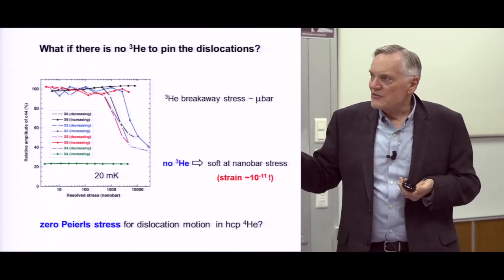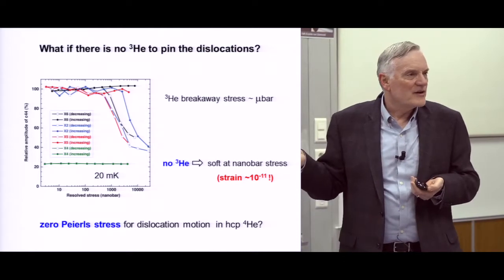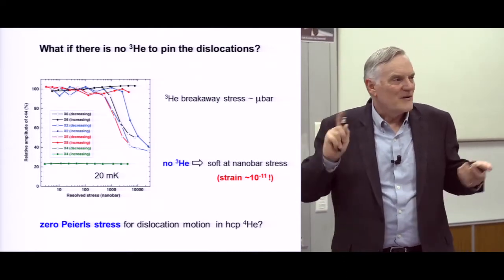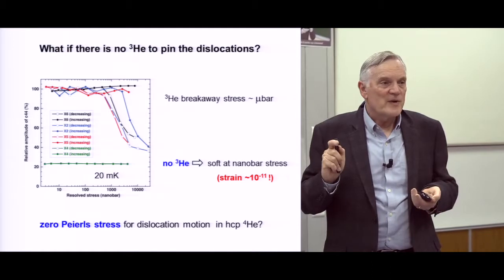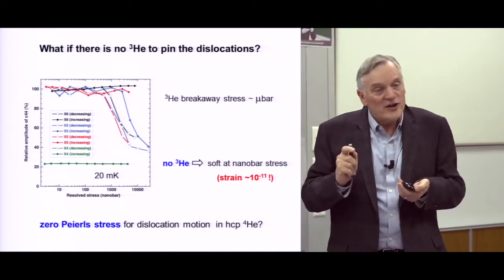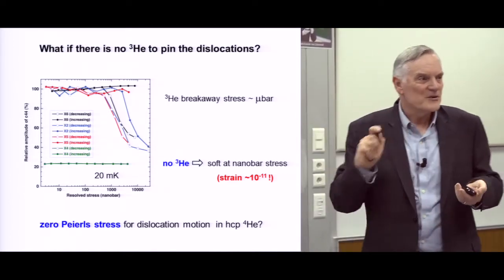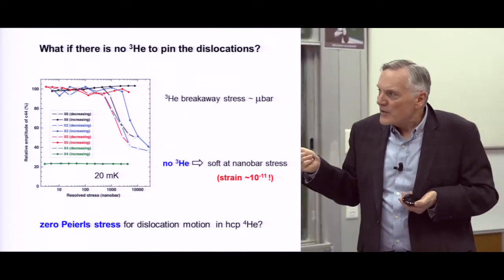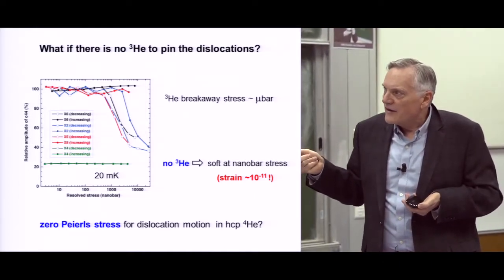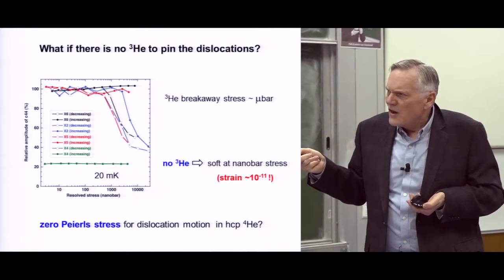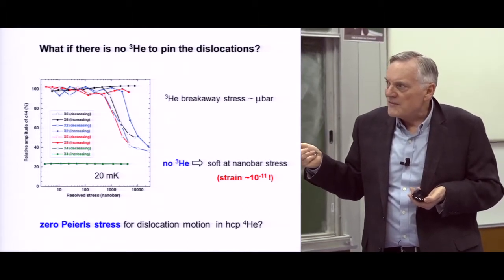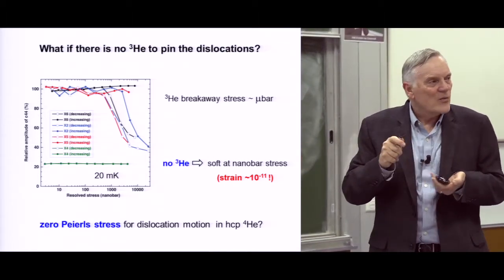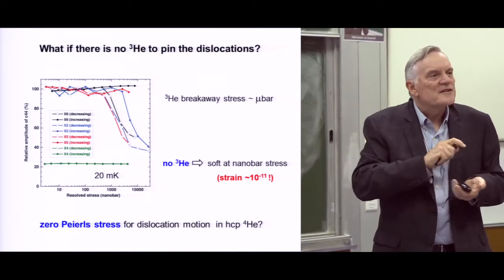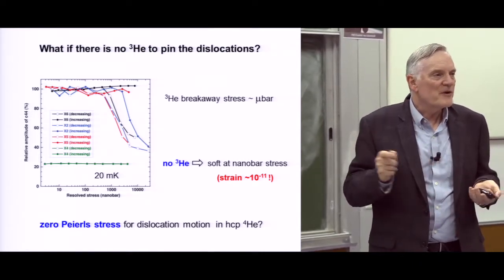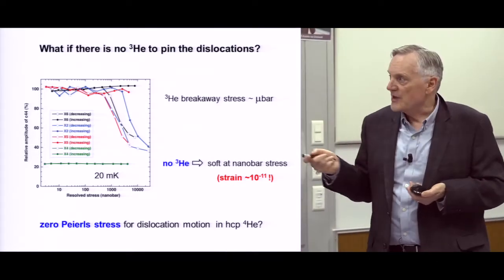But here's one that was grown at low temperature from high isotopic purity helium, and I won't explain in detail. There's probably no helium-3 atoms in that. I mean, you could calculate it, and it'll say none, zero. Not one, not two, but zero, I think. And what you see then is it's soft all the time. This is at 20 millikelvin, all the way down to the very lowest place we could make the measurement, lowest stress, the most gentle way we could do it, the smallest force, it still moves freely. The dislocation still moves perfectly freely at the smallest stresses we could apply.